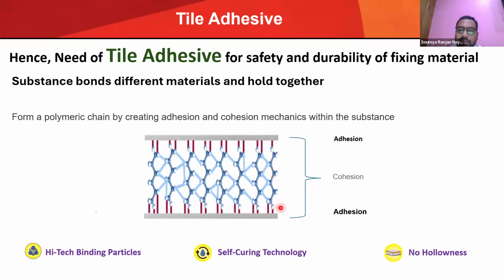What happens? Tile adhesive will give a cohesion between the substrate and the tile. Tile adhesive is a material which has a self-curing technology. We know it requires no curing. Also, it has dual shrinkage property. What happens? It will adjust its shrinkage at the time of hardening. So that means at the time of laying, the tile adhesive is fresh, and when the tile adhesive gets hardened, the area will not shrink. The area the tile adhesive covers at the time of application will remain the same.